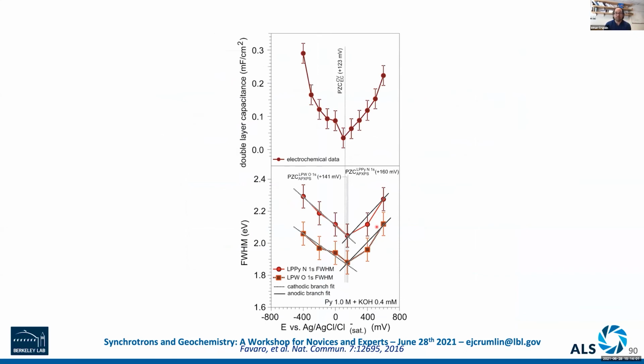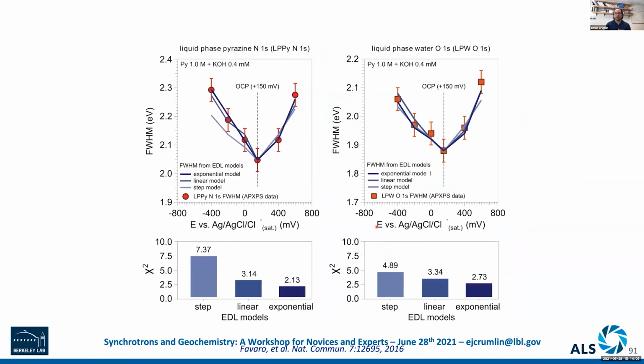So now we can see this spectroscopically, and we can also fit the shape profiles of this to extract out the potential distribution. We can really establish that in these kinds of dilute regimes, we're seeing this exponential drop, which is consistent with the Gouy-Chapman-Stern model of these solid-liquid interfaces. And this is something we can directly probe very clearly and well.